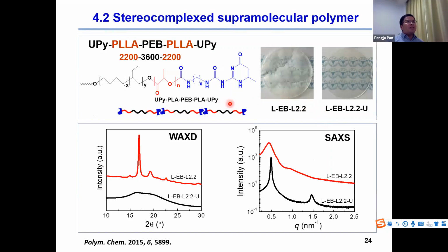We also use the stereocomplex crystallization to modify the physical performance of a supramolecular polymer. To prepare the supramolecular polymer, we first synthesize the hydroxyl-terminated low molecular weight PLA-PEB-PLA triblock. PEB is a soft block and it is a random copolymer of ethylene and butylene. We then introduce the hydrogen bonding UPy group to the chain end. The UPy hydrogen bonding can extend the polymer chain and form the supramolecular polymer.